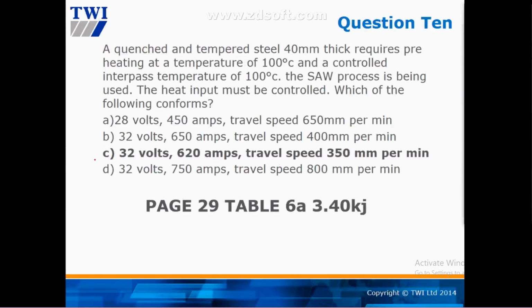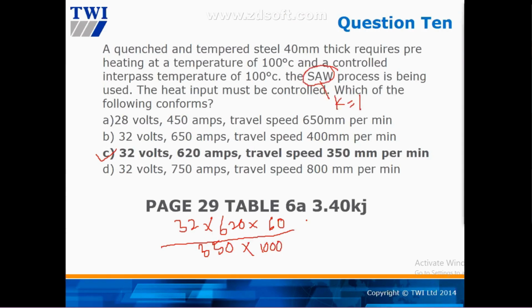Then when you do calculations, C is the best answer, right? Because from this, 32 volt, the heat input is 32 times 620 amps per minute here, then we times 60 divided by 350 times 1000. Because for SAW, the K factor is equal to 1. So it doesn't matter. Whatever arc energy you got here, you times 1, the heat input is still the same. Yeah?